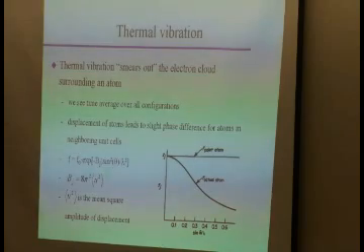Now, why is that? Well, if we go right centrally through an atom, so this would be a scattering angle of 0, a tiny little bit of movement won't make much of a difference. If we scatter at a higher angle, all of a sudden it does make a difference for the phase difference. And that is what it all depends on. Do we get a phase difference from two atoms that are slightly displaced? So, the higher your angle, the more thermal vibration will actually affect your scattering amplitude.